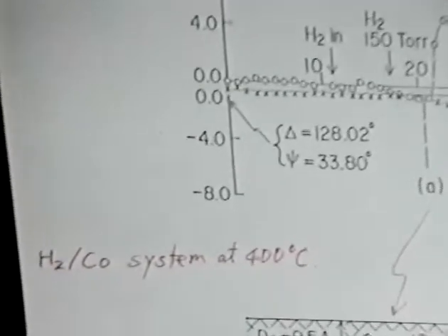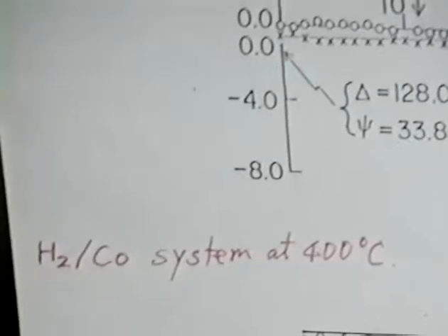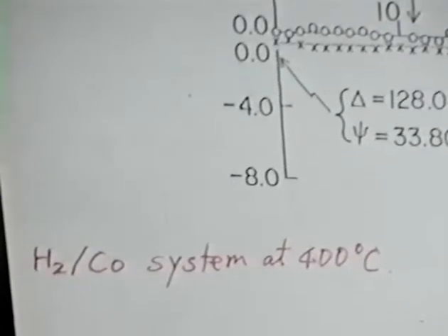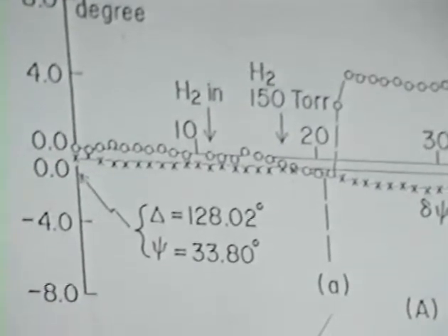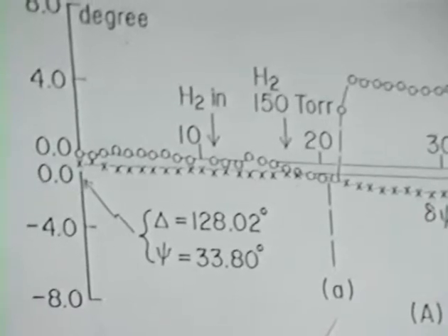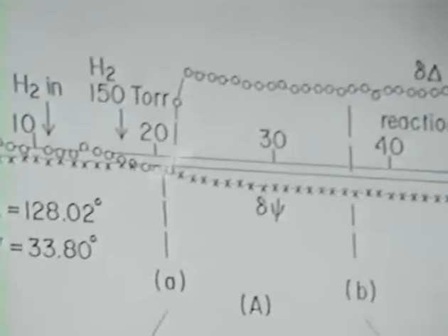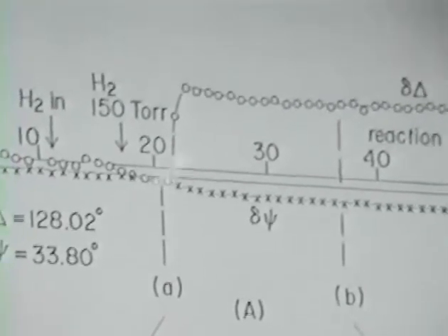Such a behavior might be somewhat specific to the iron side. So I want to demonstrate the case of the absorption of hydrogen on cobalt surface at 400 degrees C. This case effect is somewhat different, but basically, in stage A, we have a subsurface hydrogen, because in this case also the delta is negative, which means perhaps no adsorbed layer.